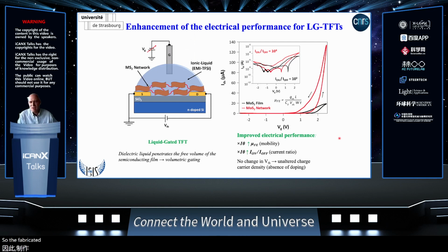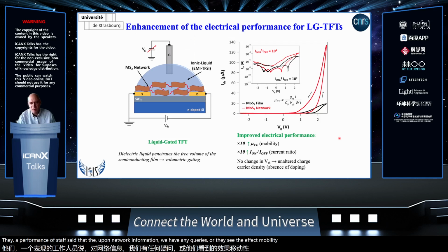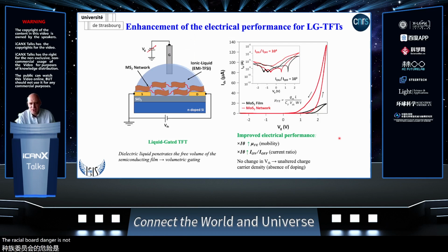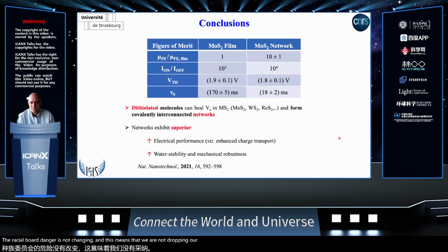So we fabricate a liquid gate TFT, and we decide to use this kind of geometry because the dielectric liquid, which penetrates the free volume of the semiconductive films, allows a good volumetric gating. Now, to make the long story short, the performance are such that upon network formation, we have an increase of the field effect mobility of 10-fold. We have an increase of the on-off ratio of 10-fold. Threshold voltage is not changing, and this means that we are not doping our system. And actually, we also observe the device is much faster in the case of the network.